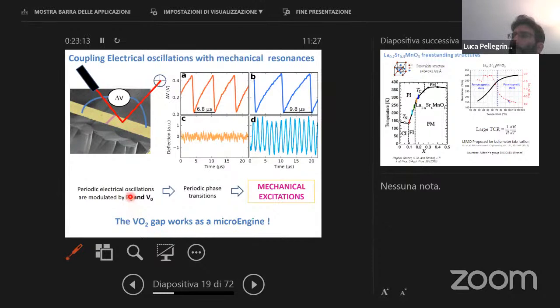And so by changing this resistance, you have periodic phase transition, and then you have mechanical excitation. So this VO2 region works as a micro engine, which is powered by a DC bias. So this could be particularly interesting if you want to do integrated actuators without electronics. I mean, we can use only DC bias, which is quite easy to make. Of course, this vanadium dioxide transition takes quite a lot of energy, because the energy associated with this phase transition is quite high,